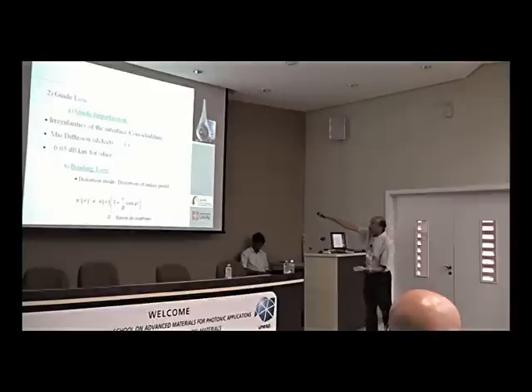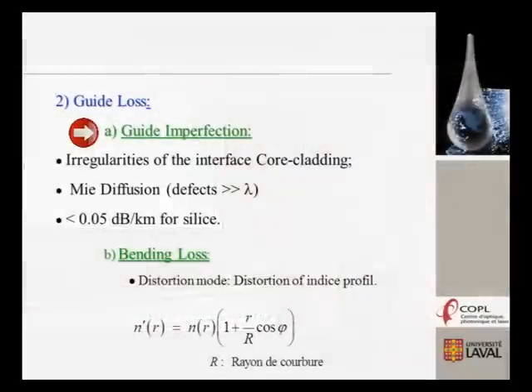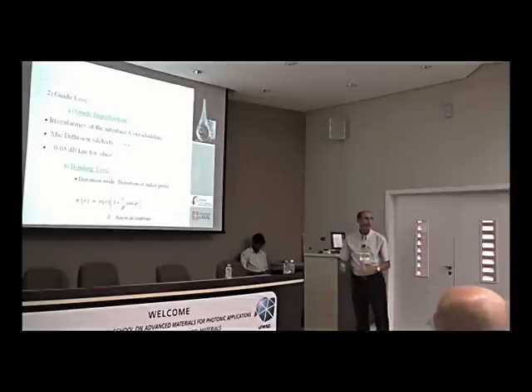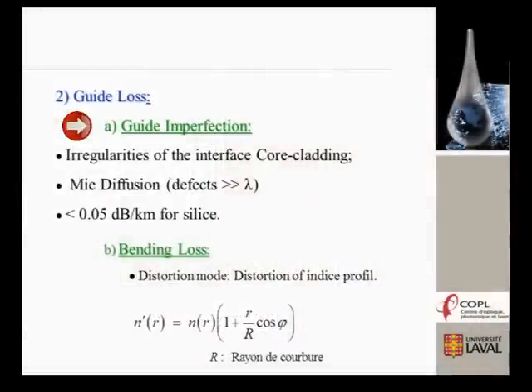You have good product, you have high purity materials, and again, the process now is a parameter of your production, because this time the imperfection is coming in the guiding of light, because sometimes we have some irregularity at the interface between core and cladding. Remember, core and cladding, we must match the expansion coefficient, we must match the viscosity of that. And sometimes, depending on the viscosity, we will have some problem at the interface of core and cladding, and this will affect the property of the optical fiber. And this defect is generally lower than 0.05 dB per kilometer for silica fiber.